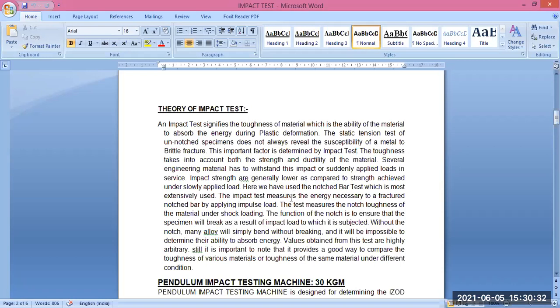The impact test measures the energy necessary to fracture a notched bar by applying an impulse load. You know, for both Izod and Charpy, there is a triangular notch over the bar itself. This gives us an opportunity to break the bar at the notch. And you can apply a certain factor of safety over your findings in order to design for the load, because that will be sufficient. Now, this tests the notch toughness under shock loading. So, what is the matter of having a shock loading?